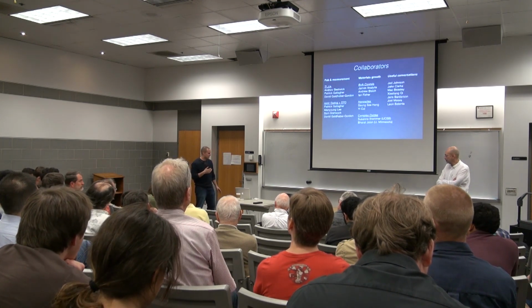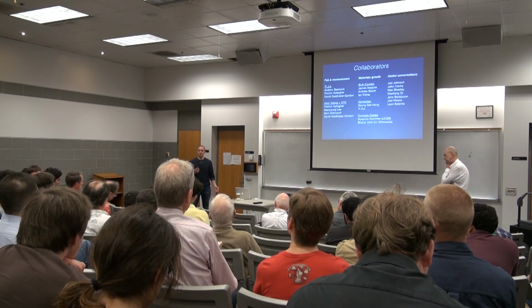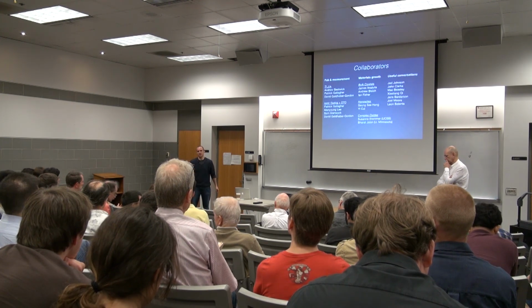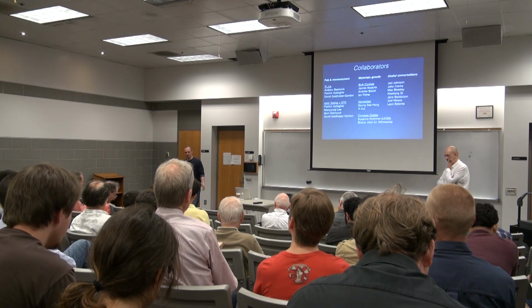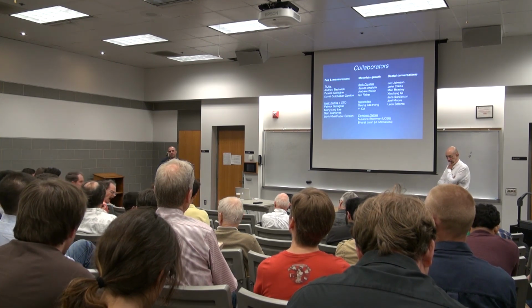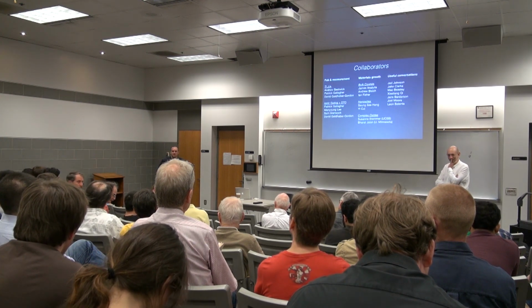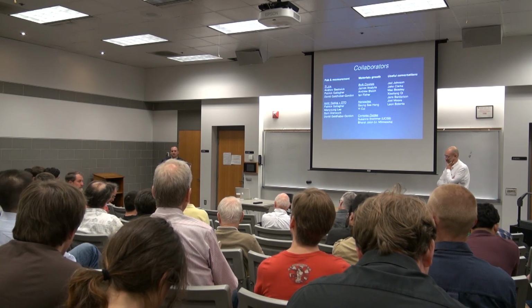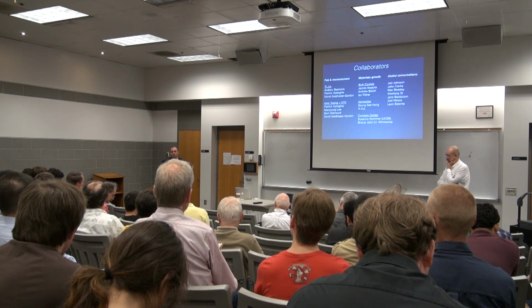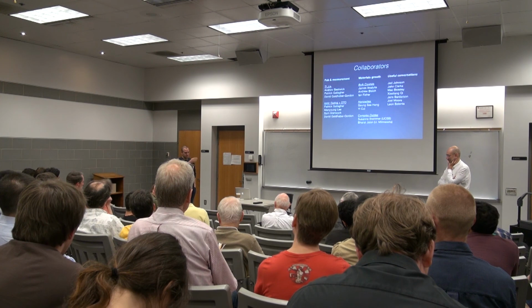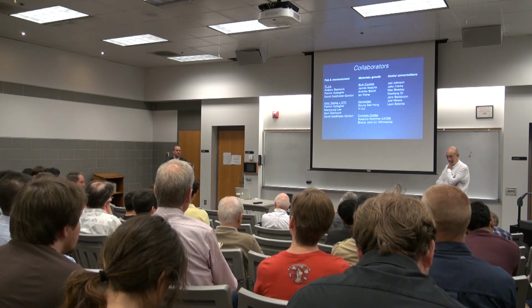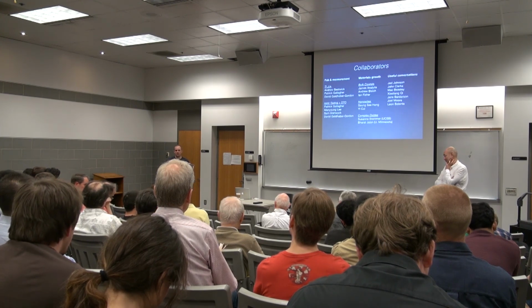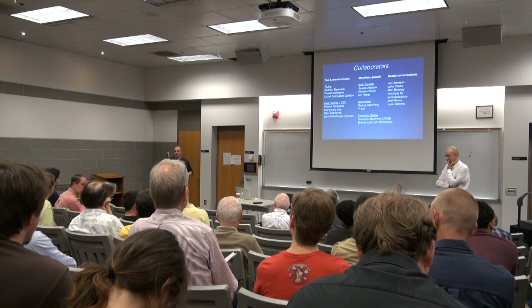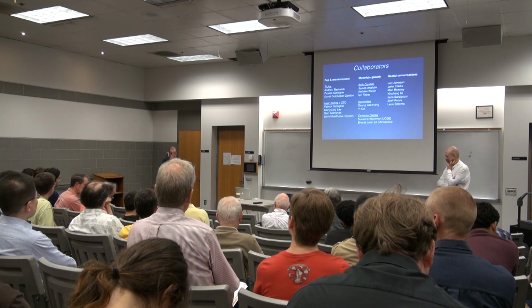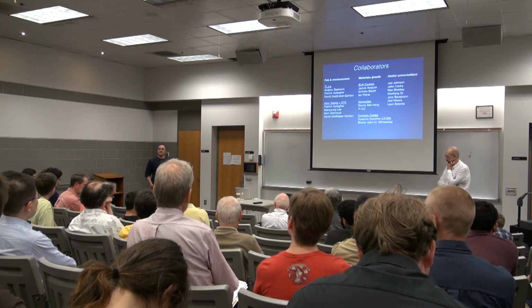Yeah, it turns out the real reason is that the spin-orbit interaction strength is just small. This is what sets the energy scale, and that also sets the minimum disorder or minimum electron density you need to see these things. The relative energy scale for spin orbit in these systems is a Kelvin, roughly. There are other material systems, some that we've put forth in our new PFC renewal, where the spin orbit strength is room temperature, and so it can really dominate the energy scales. Just get Kondo out of the problem, get funny Andreev bound states out of the problem, and really see, if we made these systems, what do we see? There shouldn't be any question about whether Majorana physics dominates or not.